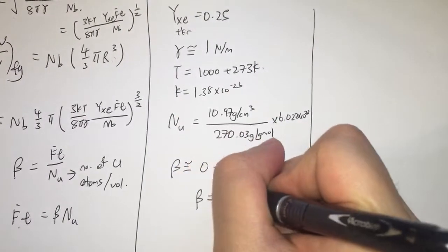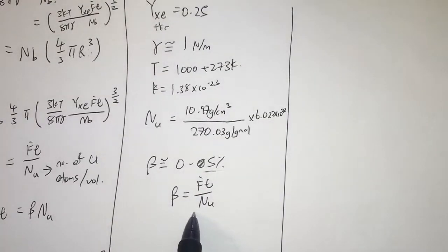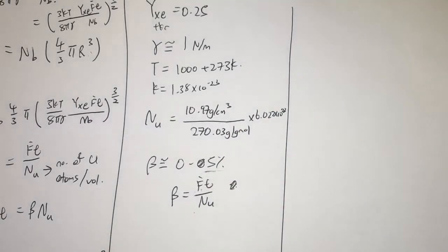Remember, while the number of uranium atoms stays the same, there are more fissions that occur. So with breeding, the burn-up may be slightly higher than, let's say, the enrichment level. And enrichment is the number of fissile atoms compared to the number of total atoms. So it's the number of uranium-235 atoms as a percentage of the total uranium atoms there.